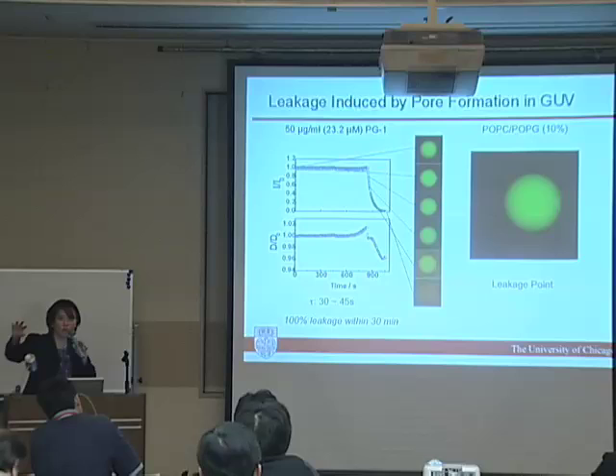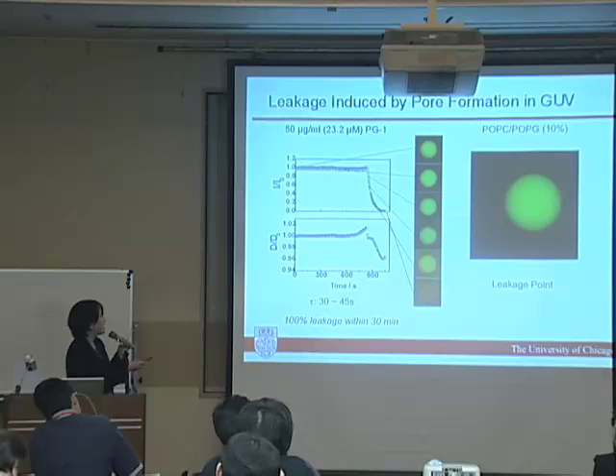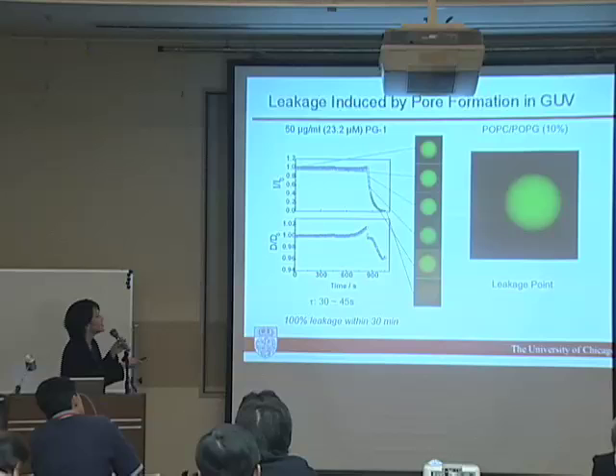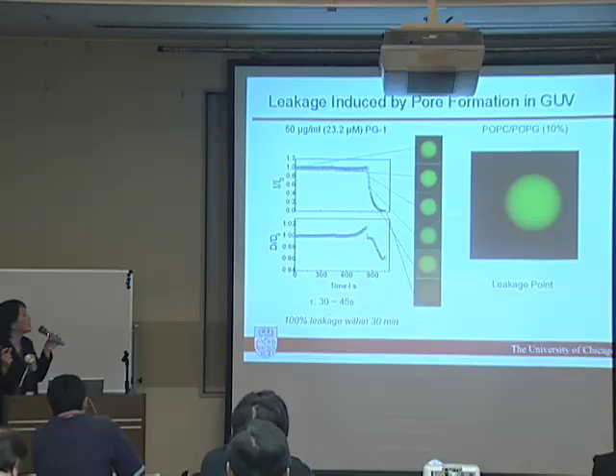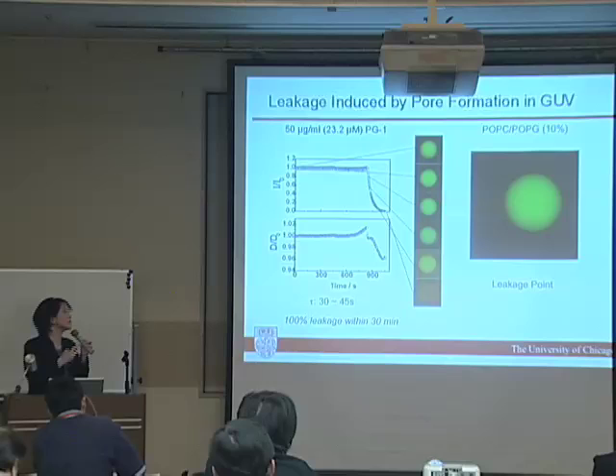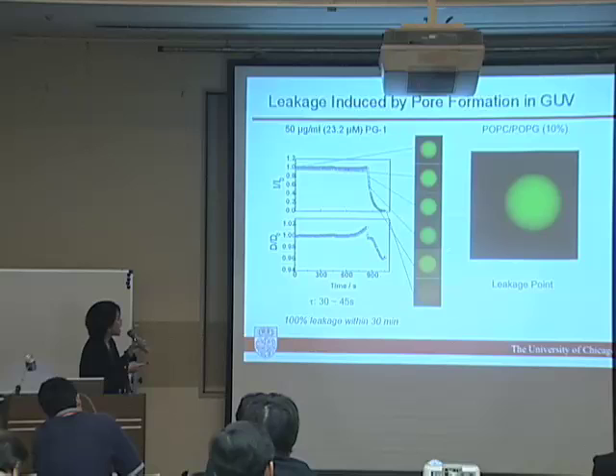So far I have shown you a two-dimensional system whereby you have a supported bilayer and we're looking at pore formation. You can also make a better mimic of the cell by moving to a three-dimensional system. What you see here is a giant unilamellar vesicle — single lamella separating what is inside. We put dye solution on the inside, and the surface of the membrane also has dye in red color. These are single vesicles on the order of 30 to 50 microns in diameter. When I subject this to the action of antimicrobial peptide, you can look at how the intensity on the inside gets plummeted because holes are being bored on the surface, so that the dye is leaking out from the inside to the outside. As that happens, you can eventually start seeing just the fluorescence from the labeling on the lipid itself.